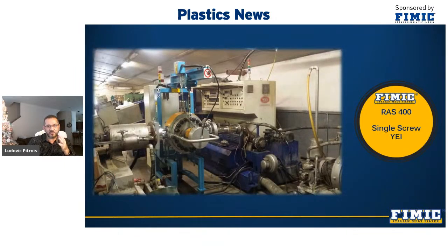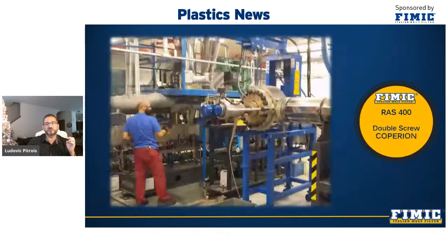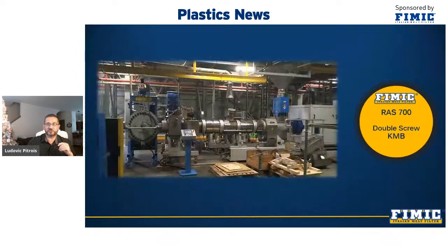In the case of this YEI extruder, unwashed LDPE with a capacity of 1,100 pounds per hour is processed with a RAS 400 filter. In this twin screws cascade extruder, Coperion, we process unwashed XPS at a rate of 2,200 pounds per hour with a RAS 400 filter.